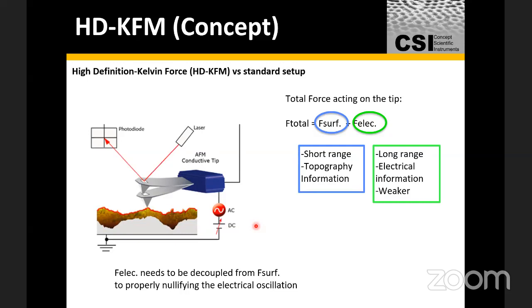So if you want to measure a short range force, like topography, you decouple it and measure the topography. If you want to focus on measuring the magnetic response of the surface or the electronic response of the surface, you're still measuring one force, but you've got to be able to decouple it. In this case, we term it the surface force and the electrical force. And obviously, the quality of the instrumentation will determine how good a resolution you get in decoupling the functional measurements that you're trying to make from the intrinsic measurement, that is, the topography of the surface. And that's what we're trying to highlight here.